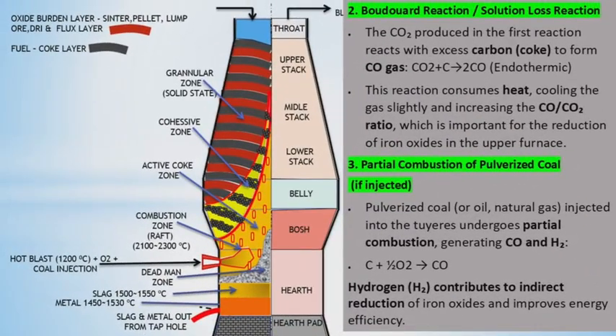Boudouard reaction or solution loss reaction. The CO2 produced in the first reaction reacts with excess carbon, coke, to form CO gas. CO2 + C = 2CO, endothermic. This reaction consumes heat, cooling the gas slightly and increasing the CO/CO2 ratio, which is important for the reduction of iron oxides in the upper furnace.